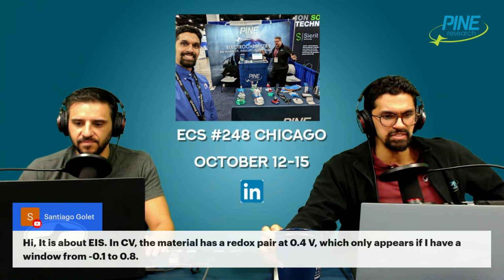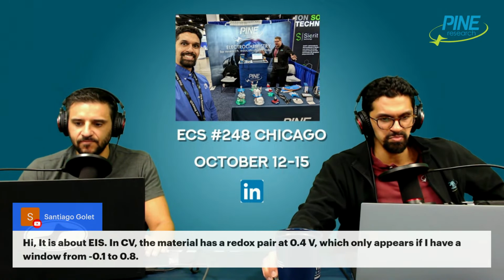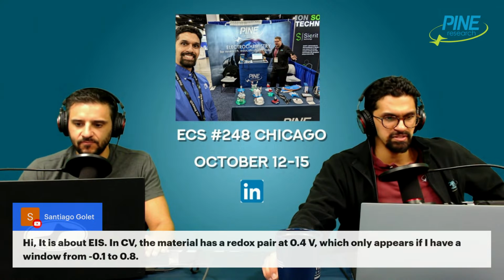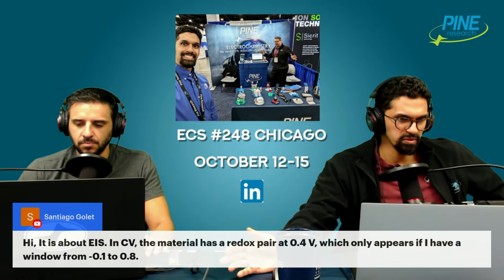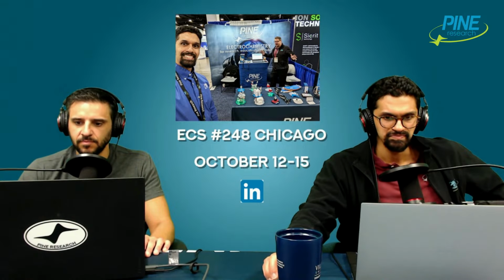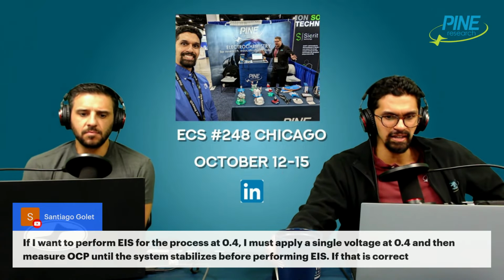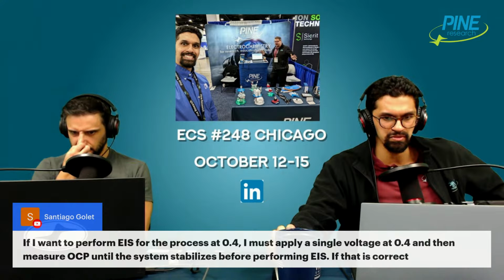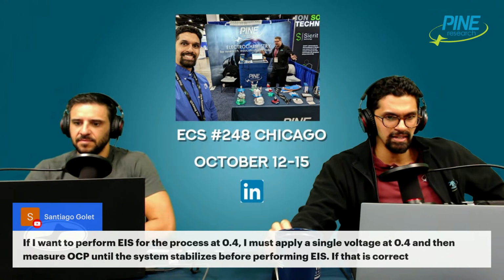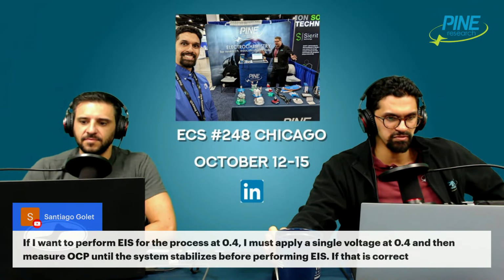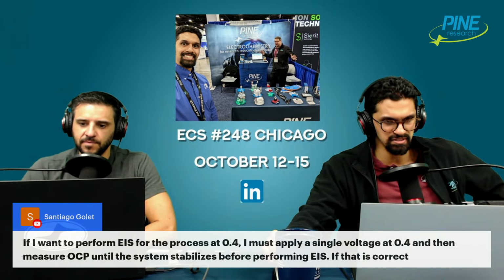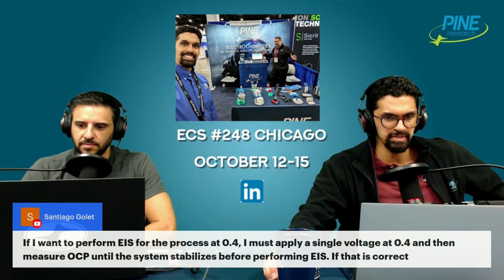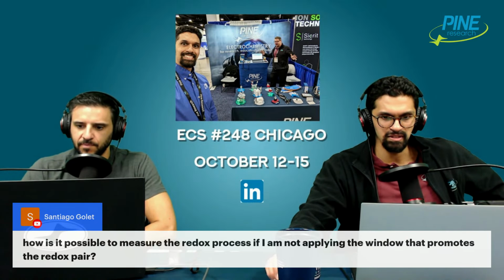In CV, the material has a redox pair at 0.4 volts, which only appears if I have a window from negative 0.1 to 0.8. If I want to perform EIS for the process at 0.4, I must apply a single voltage at 0.4 and then measure OCP until the system stabilizes before performing EIS. If that is correct, how is it possible to measure the redox process if I'm not applying the window that promotes the redox pair?